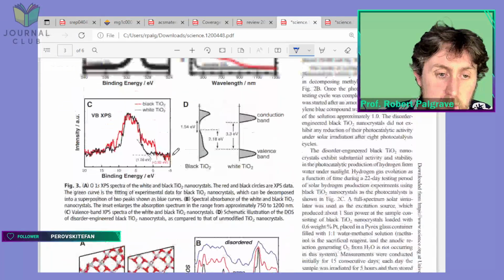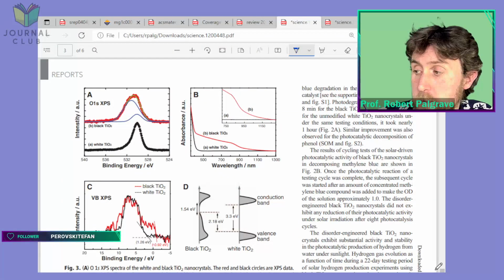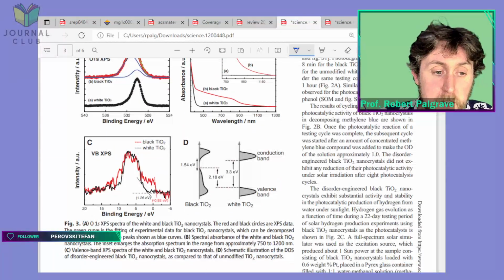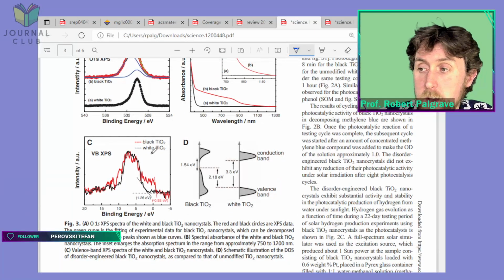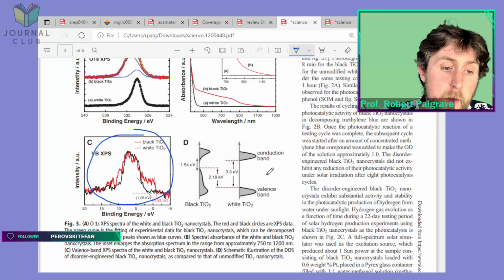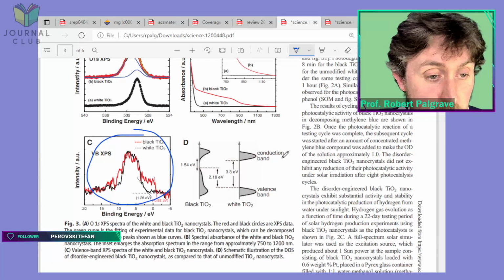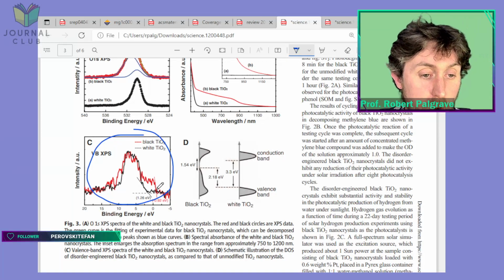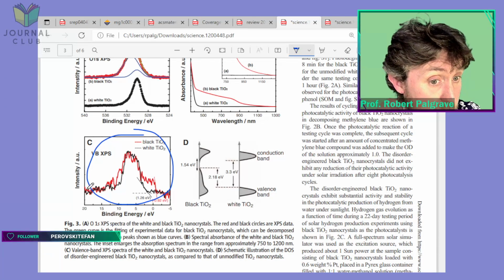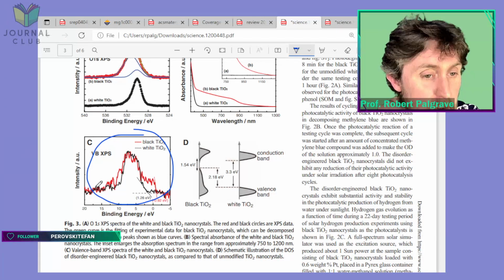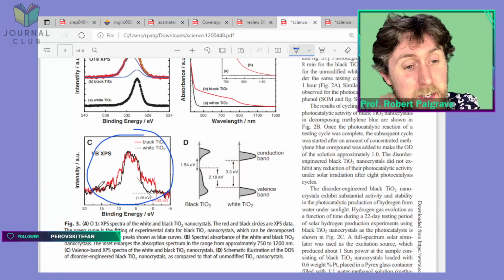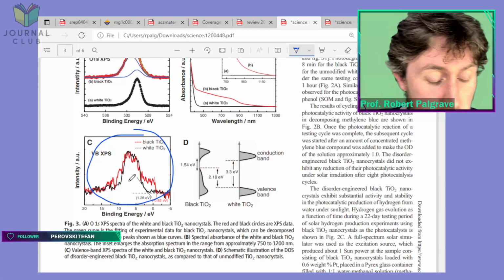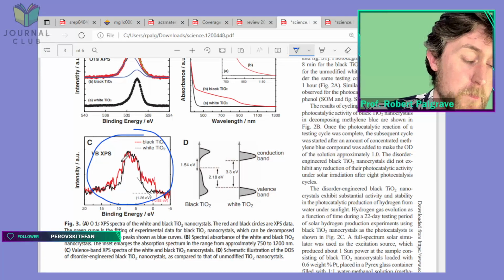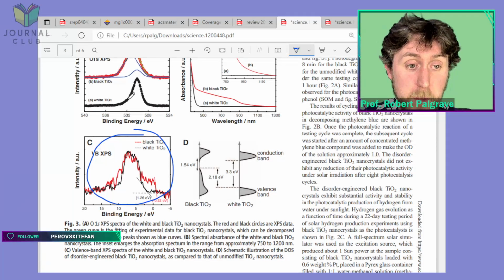But what I was going to look at was some more experimental stuff up here. So we have some photoemission spectroscopy here, and this valence band XPS especially is a measure of the outermost electrons, so it's similar to the DFT method that we showed before. One thing that really struck me about this, looking back 10 years, this is 2011, so 11 years now, is just how noisy the valence band spectra are. So valence band spectra in XPS, which is X-ray photoemission spectroscopy, the intensity is low compared to other peaks. So this is another peak you might see in XPS. This is a peak coming from oxygen.